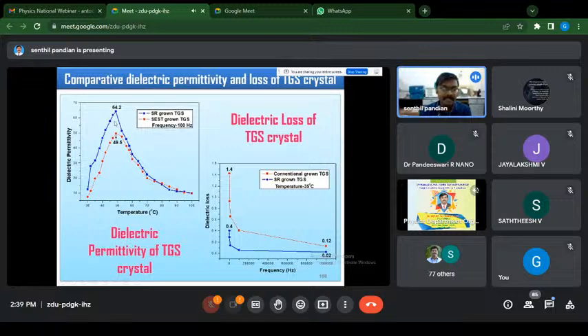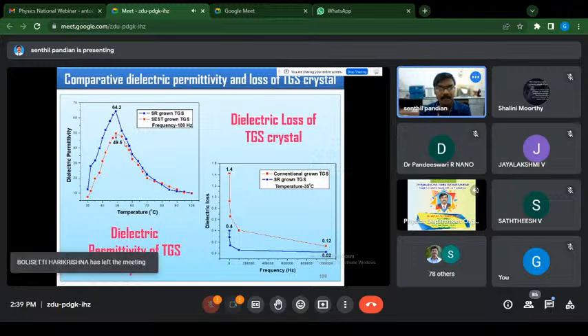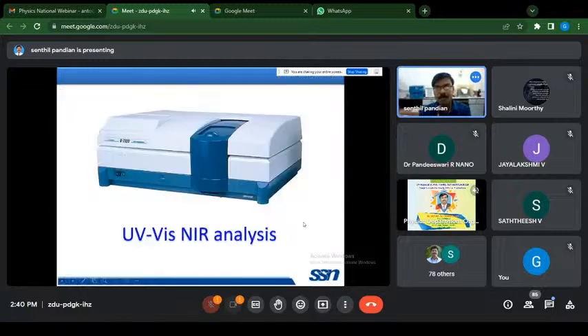And this is the TGS crystal, 49 degrees. This is the phase transition temperature. Below this temperature, the crystal is ferroelectric in nature. After this temperature, the crystal is paraelectric in nature. So when the temperature increases, the dielectric permittivity also increases, reaching the maximum dielectric permittivity at 49 degrees. The blue color indicates the SR method grown TGS crystal, with a dielectric permittivity of 64.2 for the SR method grown crystal. But in the case of the conventional grown crystal, it is only 49.5. So, the higher dielectric permittivity and the lower dielectric loss.